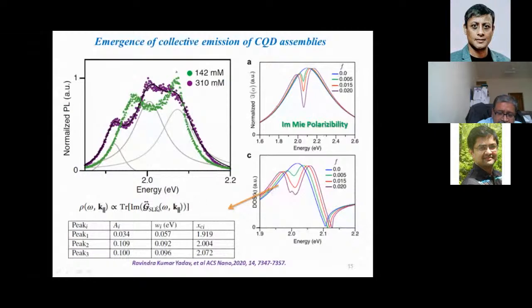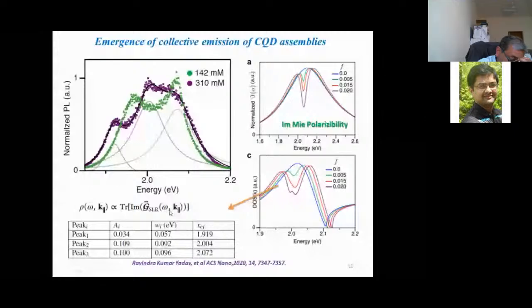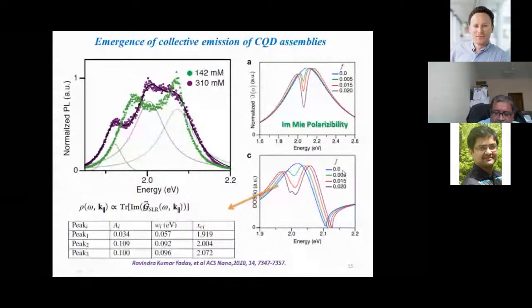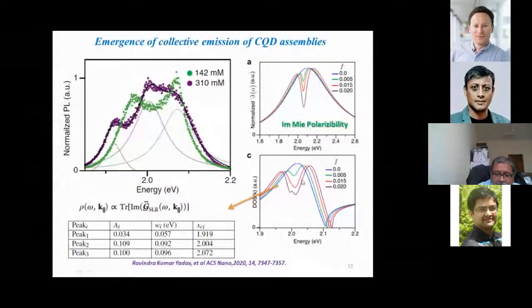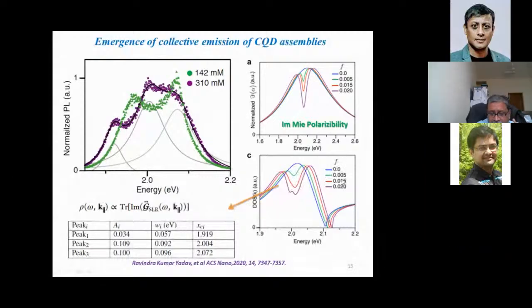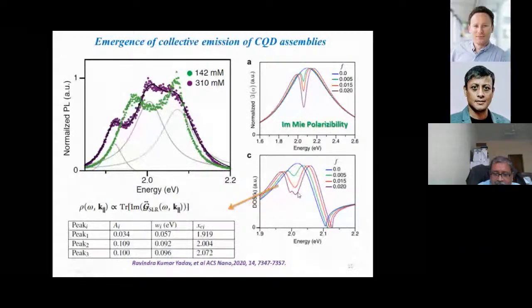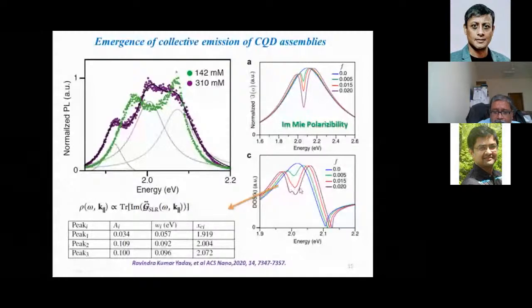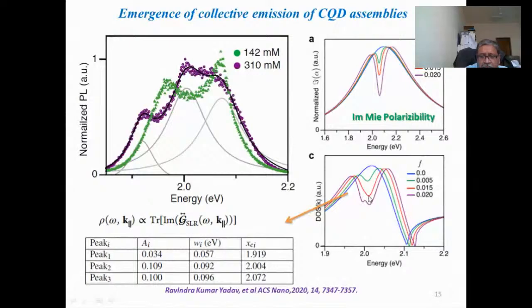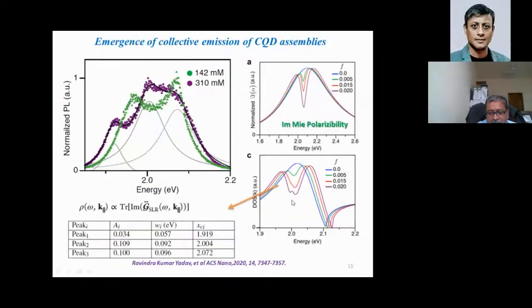But also, what is interesting is that one can calculate the density of states, using Green's function for the lattice resonance mode, where you have the full dispersion in momentum space. Again, you see this feature emerging here in the density of states. As you increase, in this case, the oscillator strength, but in our case the experiment, you start seeing the emergence of this mode or this peak here, and this is around the region of the uncoupled modes. That's interesting. You see these modes which can correspond to the upper and the lower polariton branch, but you have something coming in between, which is unique, right?